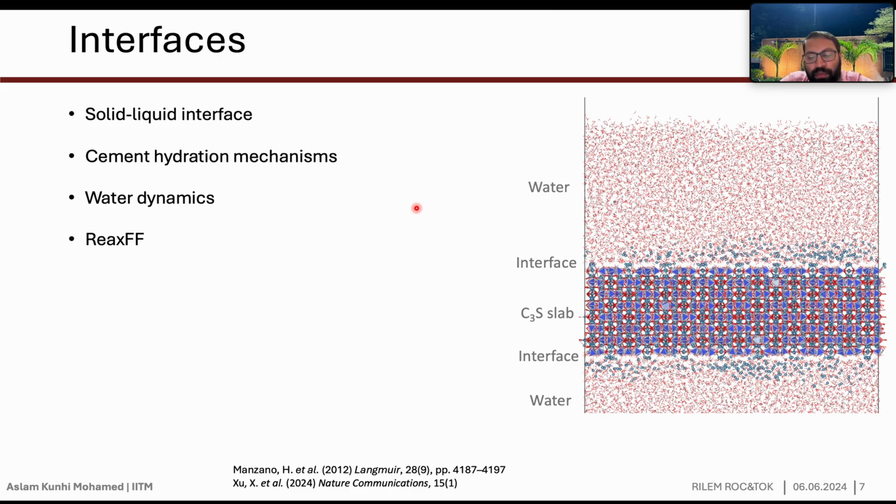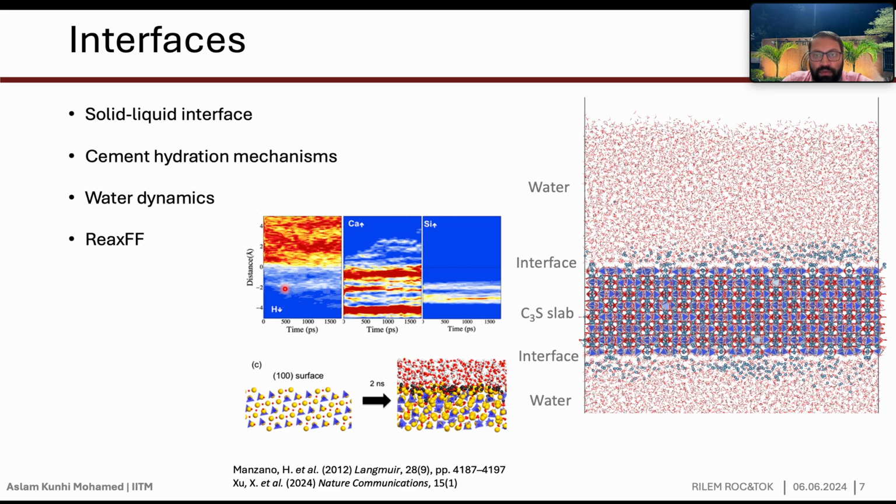Most of the time people only look at the water dynamics, or how the ions, if there are any additional ions that you put in the solution, are distributed with time. Another method is to use reactive force fields, which enable bond making and formation. Essentially, instead of hydroxylating, the water molecules will automatically come and break into hydroxides, and the hydrogen can go into either the oxygen of the silicates or just the oxide ions, for instance in C3S.